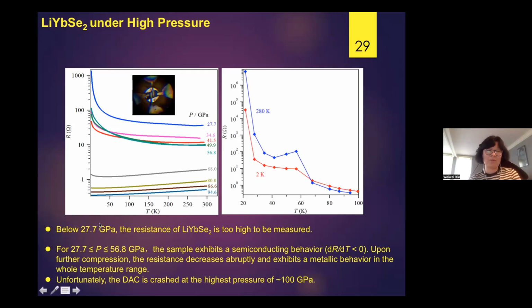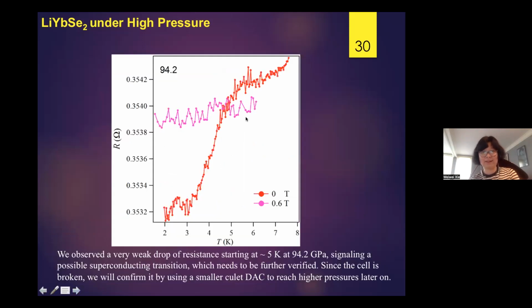He kept pressing until almost 100 GPa, and then he started seeing the superconducting signal at 94 GPa. Then the diamond was broken. I said, okay, we can keep pressing, because the idea we were thinking about is for the quantum spin liquid: as we keep pressing, the band gap will close, then some flat band will come and superconductivity will appear. So we will keep doing this work.